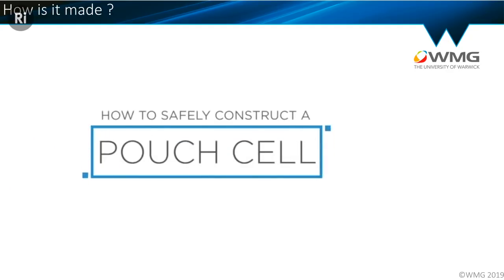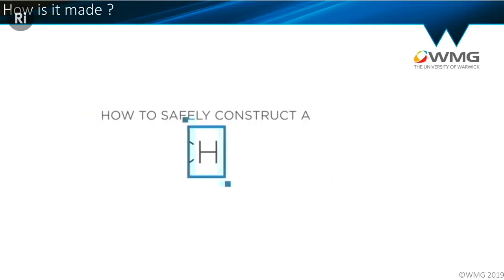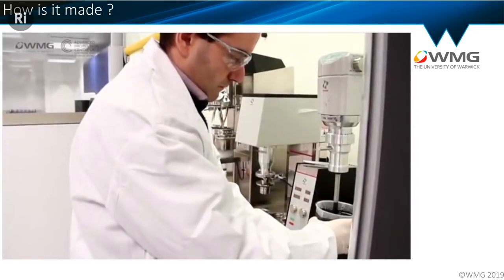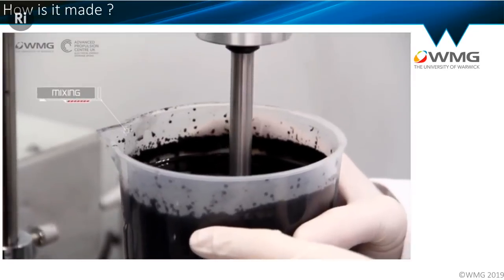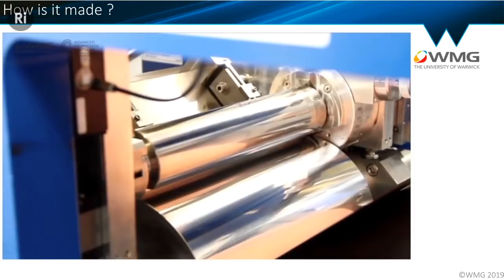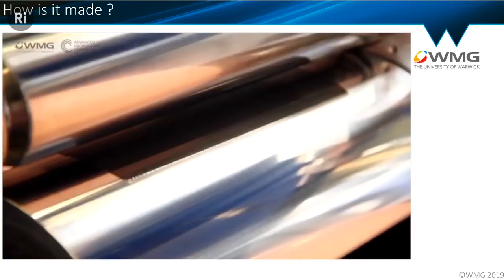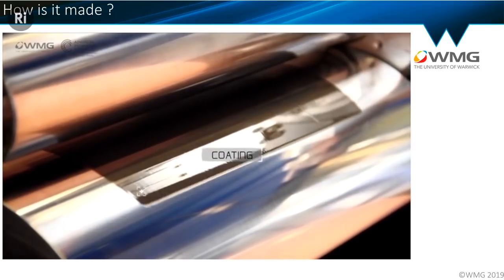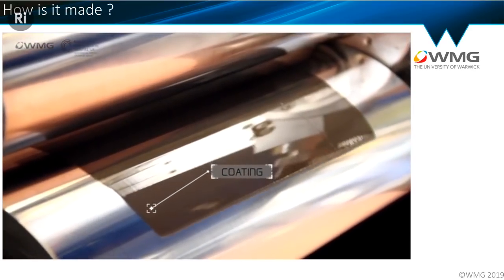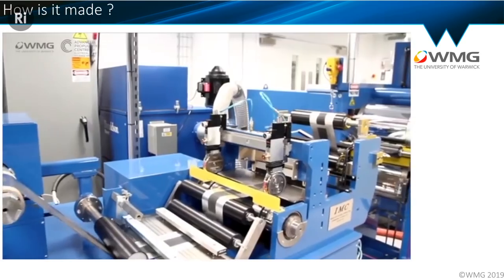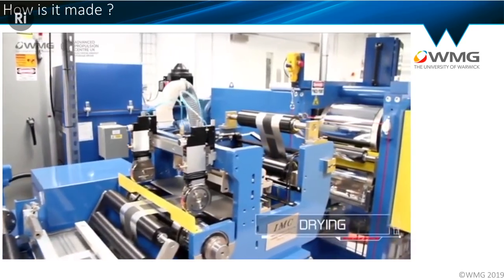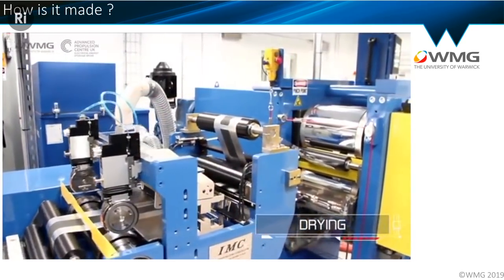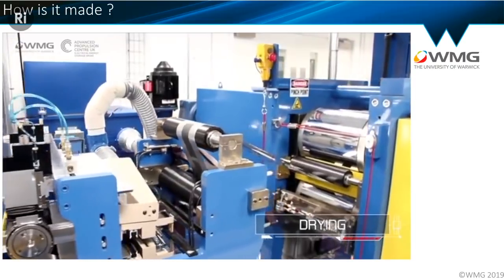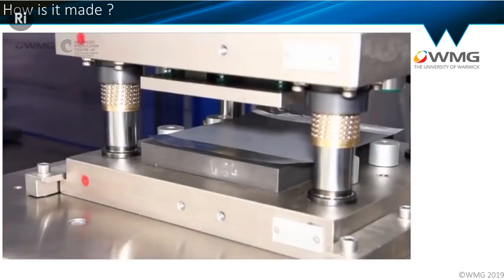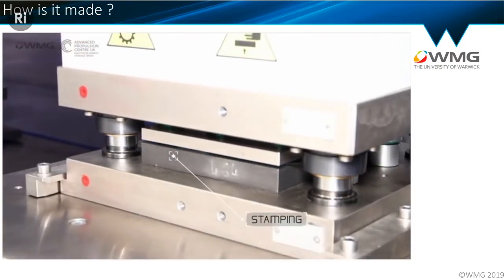Thank you very much. So what you can see here starts off with the mixing process. This is done in a lab environment. This is not what a factory looks like. So we're mixing up that ink, which is a bit like a kind of molasses type consistency. We then pour it into a reel-to-reel coater where we lay that coating down onto a roller. We draw the foil up against it, and that draws off the coating to give us the coated foil that we're looking for. The drying actually takes place in a closed cupboard that you can't see, and then we stamp